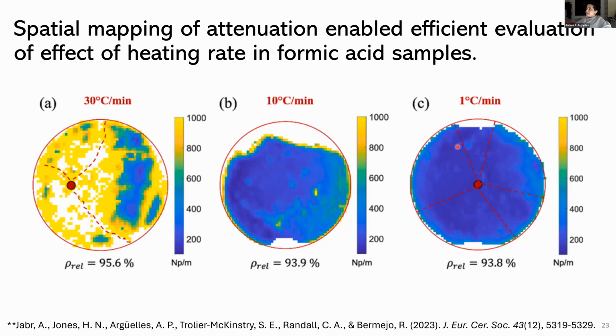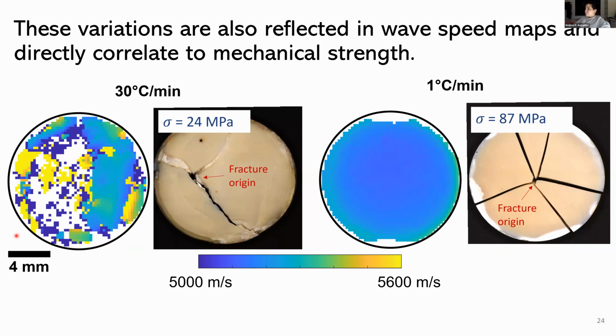And what you see in the dashed line is actually the fracture pattern that we saw for each of the samples. These were all ball-on-3-ball mechanical testing. And for those of you that might not be as familiar, essentially the ideal pattern we would be looking for would be something like this. And in the samples that were processed more quickly, we were getting a pretty off-axis pattern of behavior in the response from the samples.